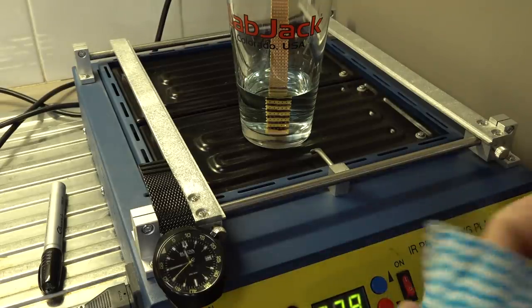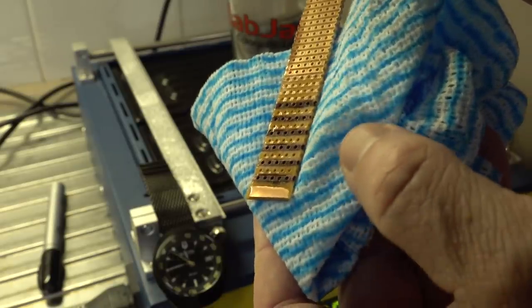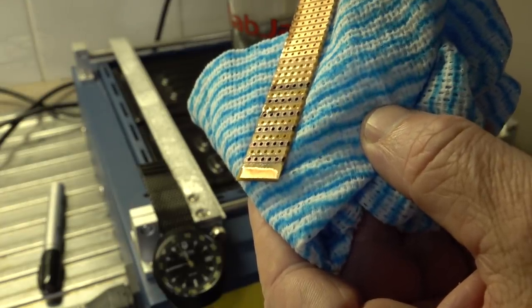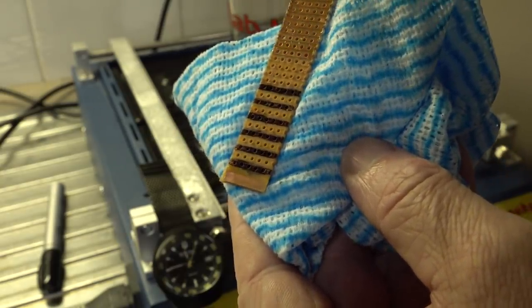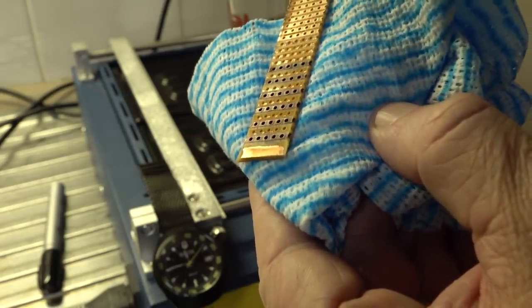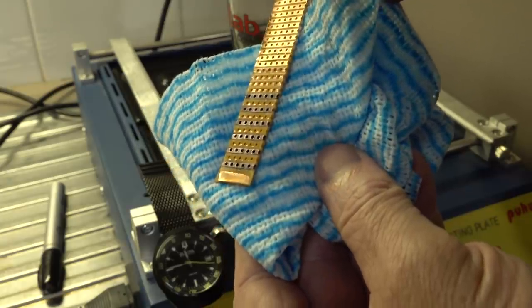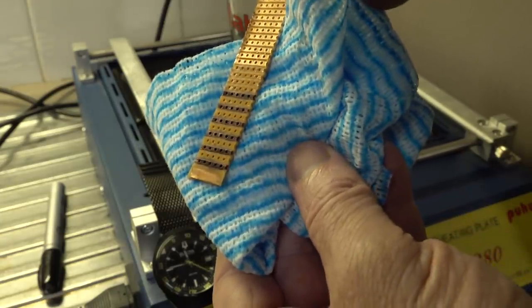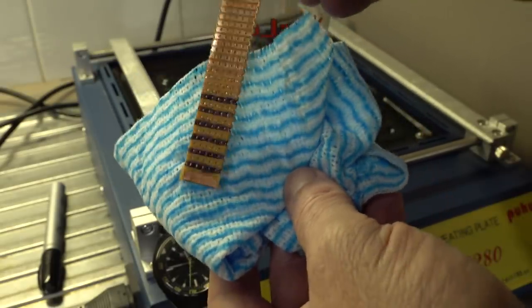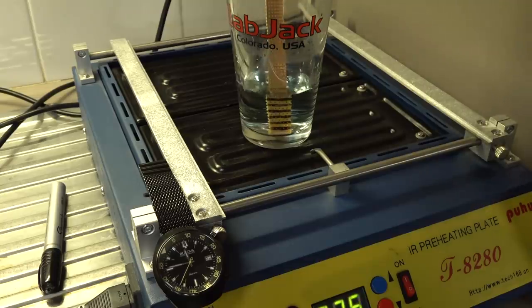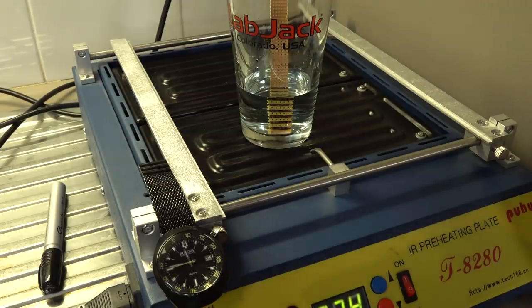Woohoo! Look at this. Almost an hour later. There ain't much copper left on those traces. The big bulk one down the bottom, of course, that's gonna take longer to etch away because it typically etches from the outside inwards. And so that's a larger amount of copper. So you'd expect that, and you see that on typical etching. But this works! It actually works! Concentrate! I mean, it's very dilute. We're almost an hour now. This would have been done in five minutes with a proper concentrated ferric chloride. But if you try and concentrate it, in this case using the magnet, there's probably better ways to do it. Then you can actually etch your PCBs with water! That is brilliant!